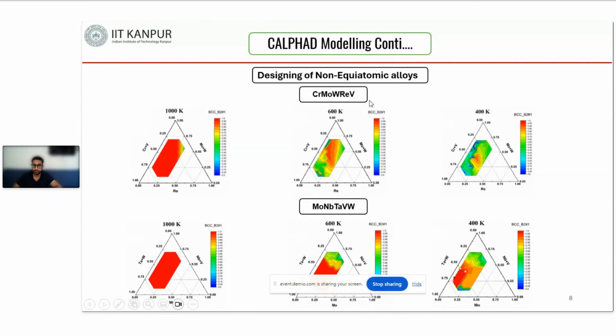We predicted their thermal stability, and we have shown the thermal stability of the phases in the form of a ternary phase diagram. If you can see here, it is a pseudo-ternary phase diagram at 1000 Kelvin, 600 Kelvin, and 400 Kelvin. Now, how to understand this phase diagram? If you see, there are different colors here, and the red color shows those alloys which give a 100% single phase structure. So if it is showing red, that alloy is a 100% single phase structure.